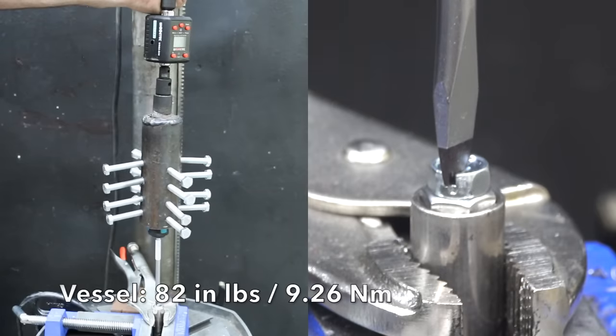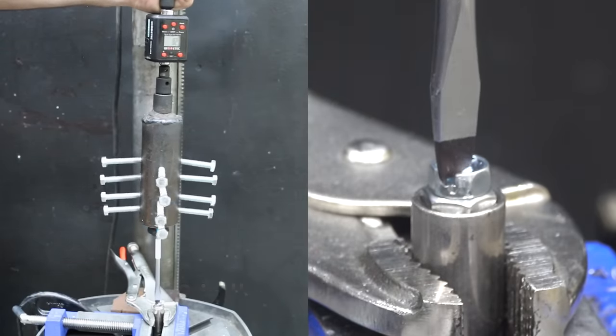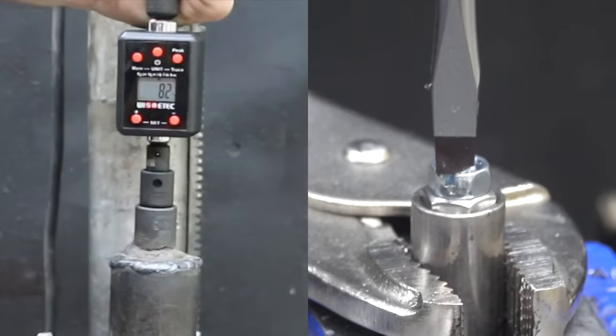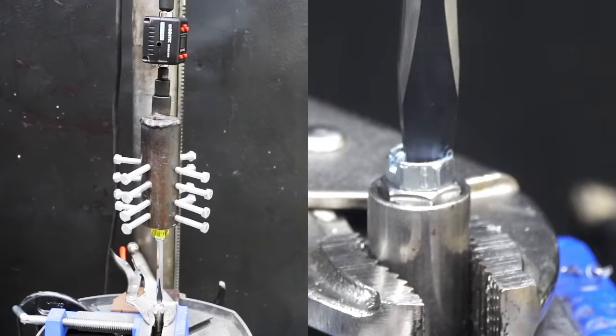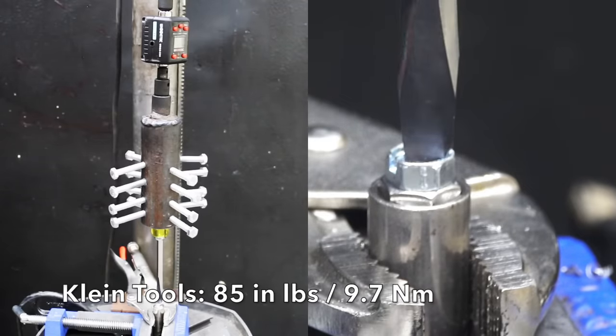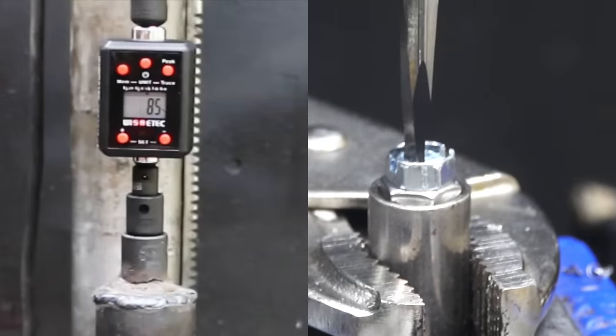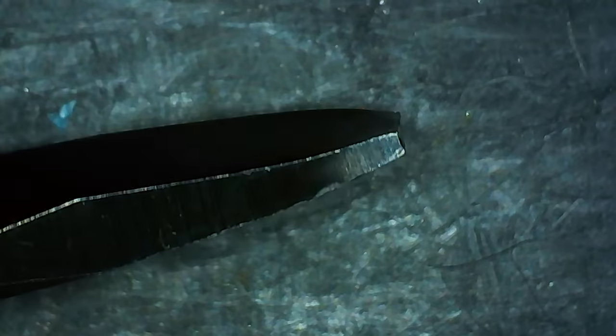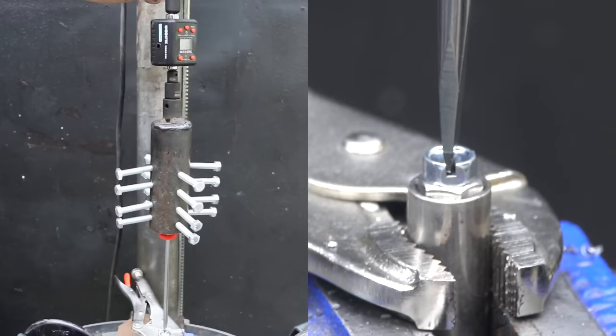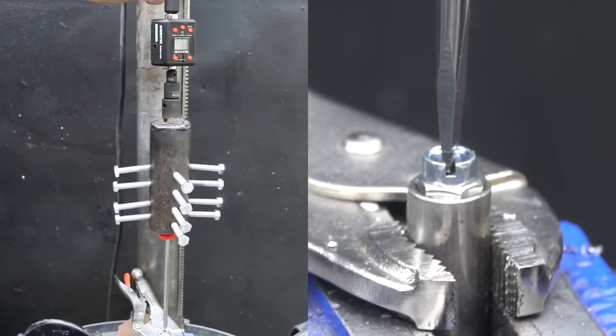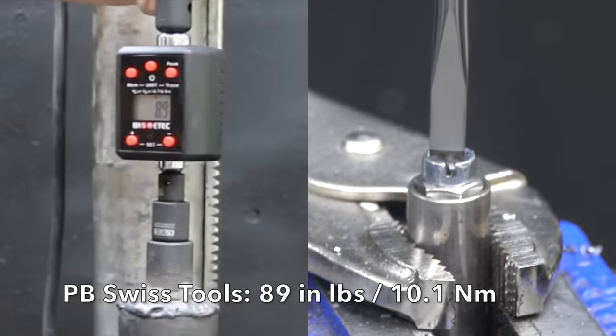Vessel has a relatively thin blade at 1.05 millimeters, and the blade lost grip at 82 inch pounds. The blade experienced a pretty bad bend. Klein Tools has one of the thinnest blades yet at only 1 millimeter. And the blade gave up at 85 inch pounds, which is actually pretty decent considering the blade thickness. And the blade experienced quite a bit of bending during the test. Just like the Klein Tools brand, the PB Swiss screwdriver is one of the thinnest in the lineup at only 1 millimeter.